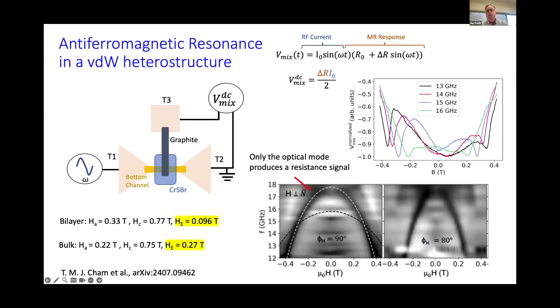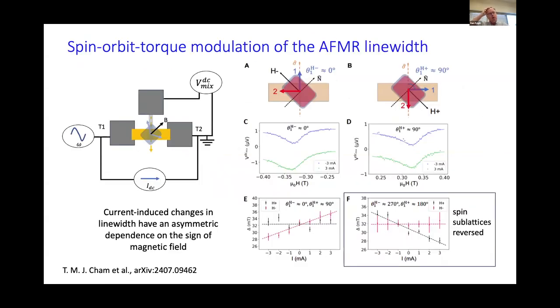And you can map out what these modes do as a function of magnetic field applied at various angles. And from that, work out the anisotropy and exchange parameters for the 2-layer magnet and compare that to the bulk. We've done that. The anisotropy fields are pretty much the same, a little bit different. And the exchange field is quite different, almost a factor of 3 lower in the bilayer. But we think that comes from not having layers both above and below each magnetic sublattice, so you expect a weaker exchange. Possibly also there's some charge transfer from the layers that makes the interactions a little bit different as well. So we've also begun to look to see if we can manipulate these electrical modes through spin-orbit torque from the bottom channel.